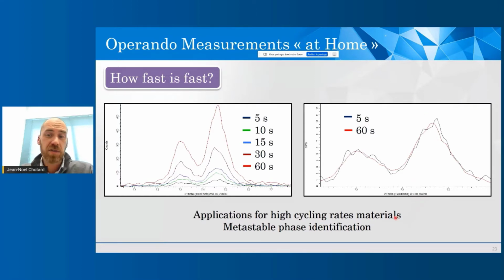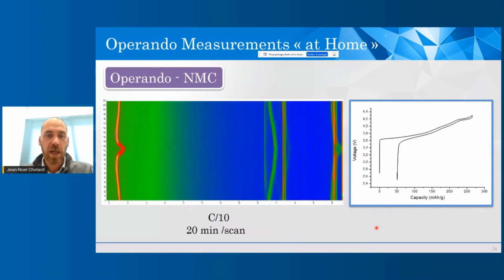This will help us to study the high cycling rate materials, of course, but also it might help to identify the new insertion and de-insertion mechanism. When we go so fast, we are expecting to see some metastable phases appearing during the cycling. As an example, you can see here the operando measurement on NMC material. Just for this purpose, I was cycling quite slowly, at a cycling rate of C/10, so I could afford to spend like 20 minutes per scan.